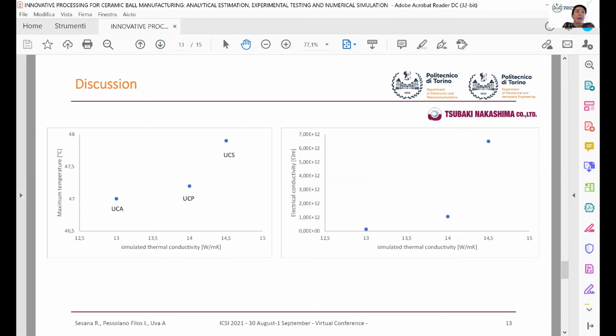As we said at the beginning, one of the goals was trying to correlate the thermal and the electrical parameters. In detail, in the left graph, the maximum temperature over the simulated thermal conductivity is reported, while in the right graph, the electrical conductivity over the simulated thermal conductivity. In both cases, we found an apparent correlation.